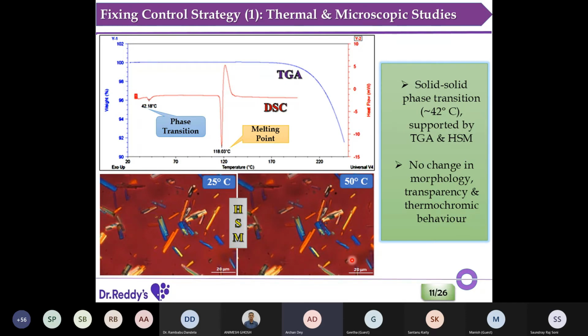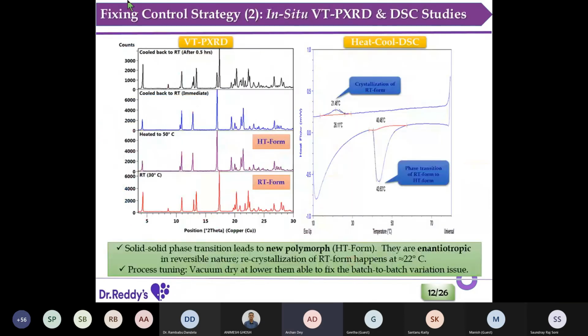In general, when a solid state transition happens, it can change the morphology, because it can happen via dissolution and recrystallization, but nothing happened here. And more surprising, there is no change in the birefringent pattern either. With this idea we did variable temperature powder XRD. What we understood is that whatever we observed in the DSC is true. If we heat the material to 50 degrees, we get a new phase, and that new phase is also indexable, which I will explain afterwards. And what happens if I cool this material back? Immediately nothing comes, but after some time the mixture comes again. That gave a big clue why the process is producing a mixture.